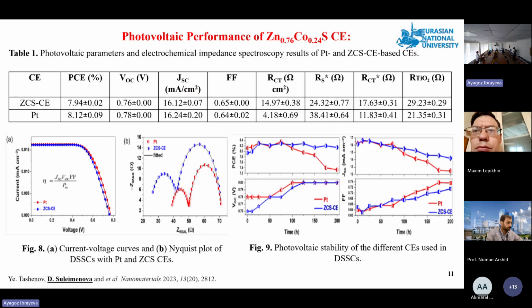The photovoltaic performance of DSSC was evaluated using J-V measurements. The extracted parameters, including open circuit voltage VOC, short circuit current density JSC, fill factor FF, and power conversion efficiency, are summarized in Table 1. The platinum-based device achieved an efficiency of 8.12%, while the zinc cobalt sulfide-based DSSC reached 7.94%, showing comparable performance with only a small decrease of 2.2%, but at a low cost.